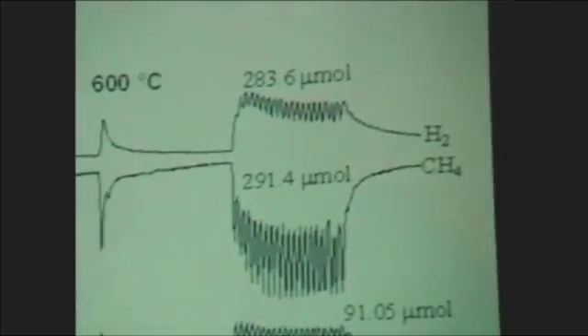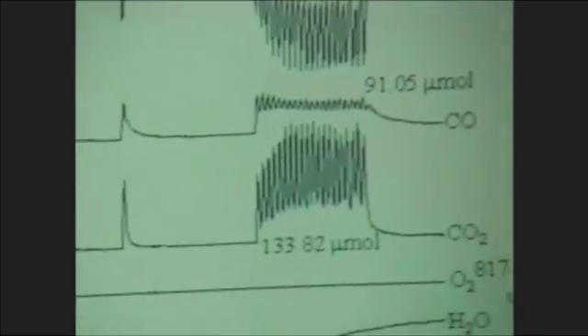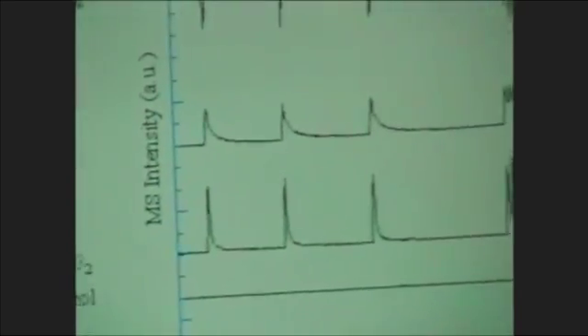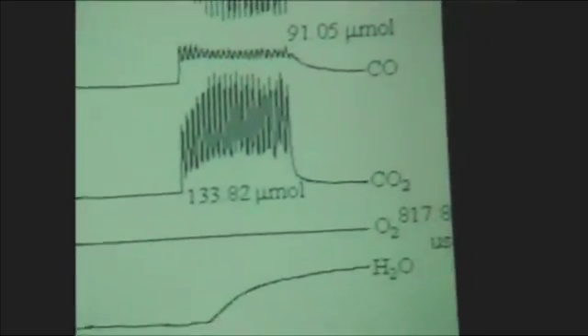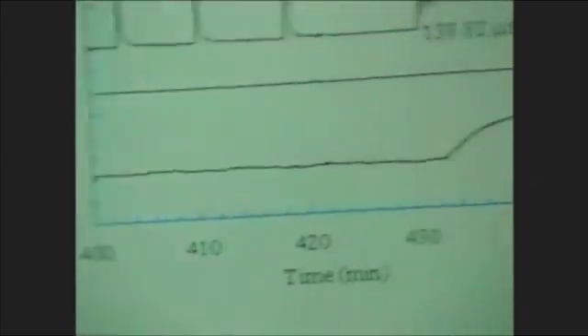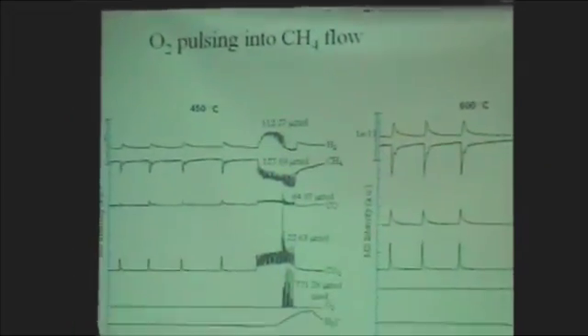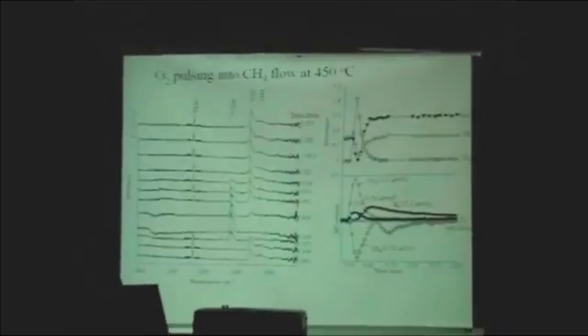This simply indicates the area below it. You can see how much hydrogen is being produced, how much methane is being degraded. In the initial pulse, we can see the pulsing of oxygen into methane to produce hydrogen and CO and also CO2. Let's take a close look at this spectrum here to see what happened and how fast this product is produced. And let's compare the partial oxidation with the reforming reaction.